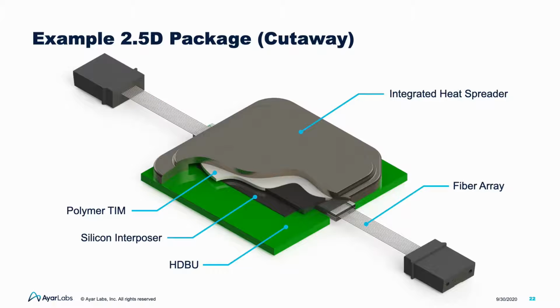Finally, we can discuss the basic form factor of the 2.5D in-package silicon photonic MCP. Note the modified organic substrate, or high-density buildup, that allows the insertion of a fiber array adjacent to and interacting with the Teraphy die. Additionally, it becomes apparent that one must control the capillary underfill, or CUF, process as discussed before. The same is true of any material used in the assembly, including but not limited to the polymer thermal interface material, or PTIM. Finally, note that this system assumes that the fiber is permanently attached to the die.